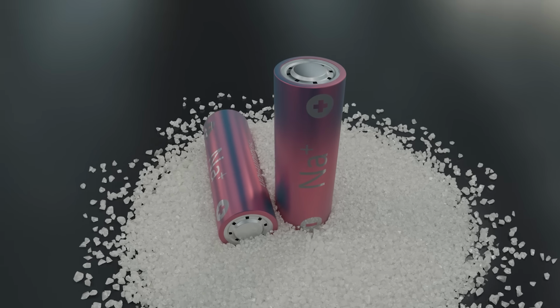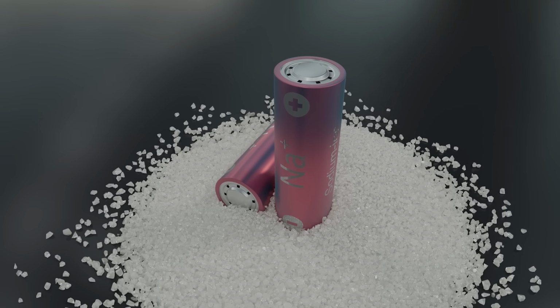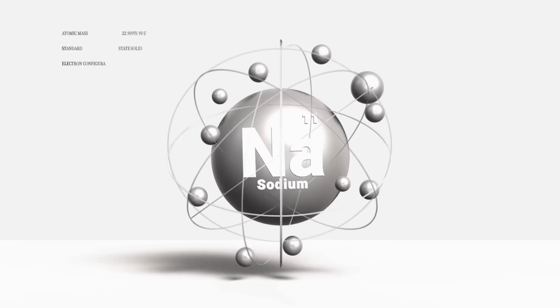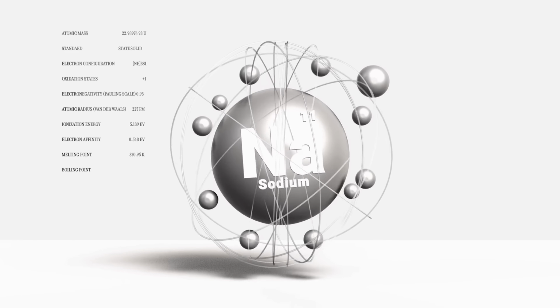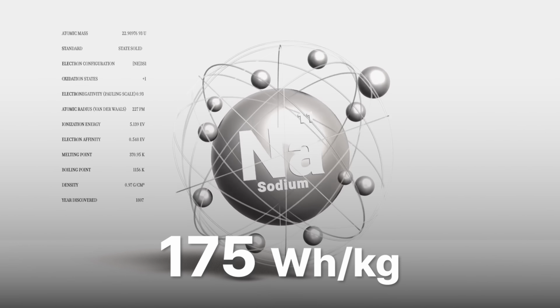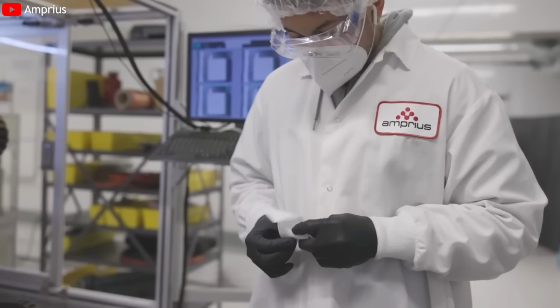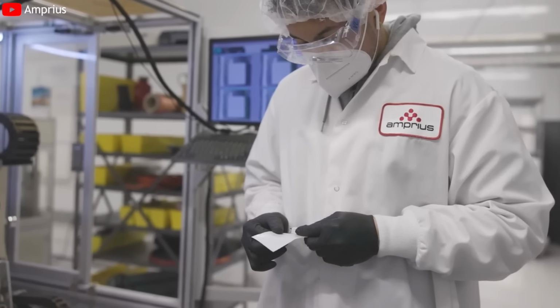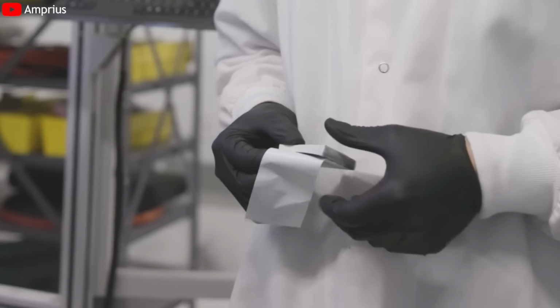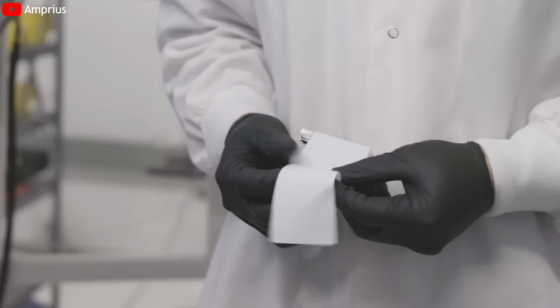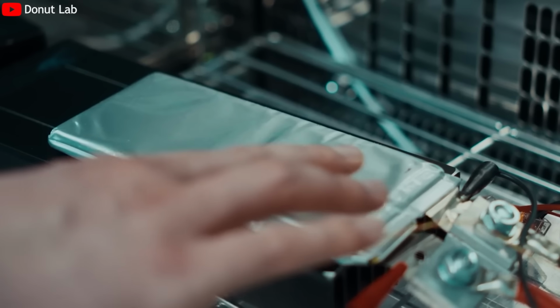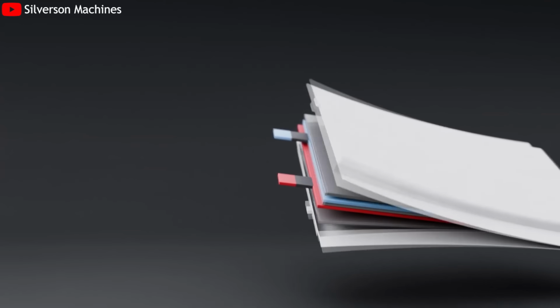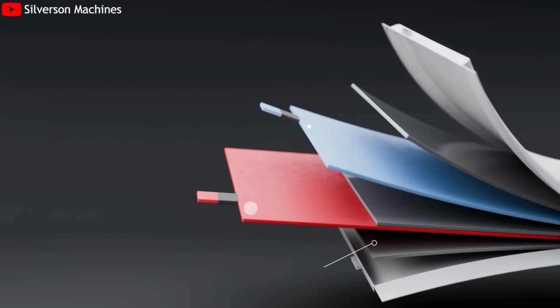However, even if the system is sodium-based, another challenge emerges. Leading sodium-ion technologies currently achieve energy densities in the range of 160 to 175 watt-hours per kilogram. A claim of 400 watt-hours per kilogram would represent a dramatic leap beyond what has been publicly demonstrated. The seal swelling behavior tells us something about safety and materials. It does not automatically validate extraordinary energy density claims. What the swollen seal truly reveals is this. The internal chemistry is unlikely to be a standard liquid lithium-ion system.